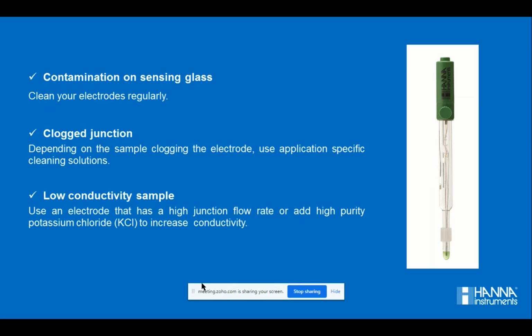Another most common problem people might face is drift in the reading, maybe because they have low conductive samples. Yes, low conductive samples like DM water or RO water will never give a stable reading in a matter of time. Yes, you have to wait for a long period of time to get a stable electrode, which might eventually ruin your electrode, as DM water has a very reducing tendency and it will leach the silica, and leach out the reference electrolyte from the reference junction as well, thus ruining your electrode completely.